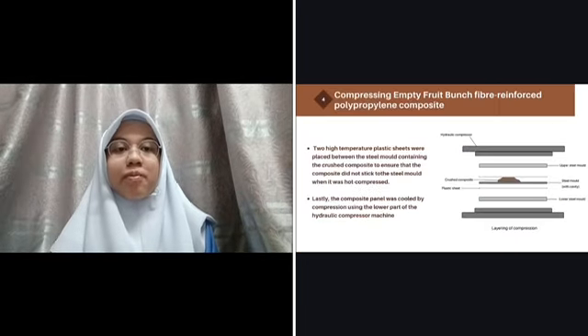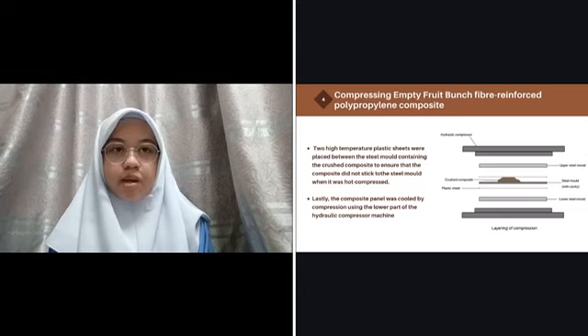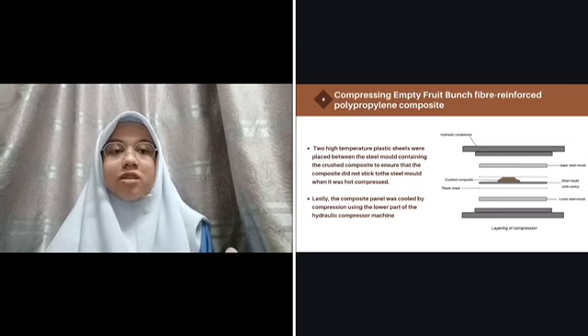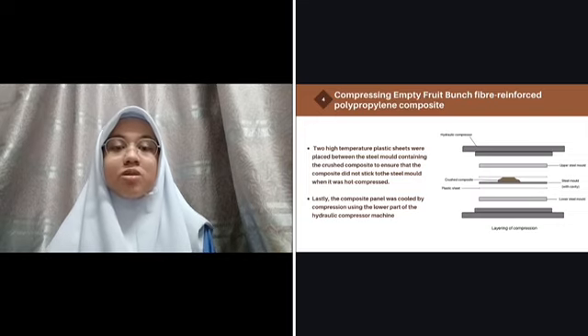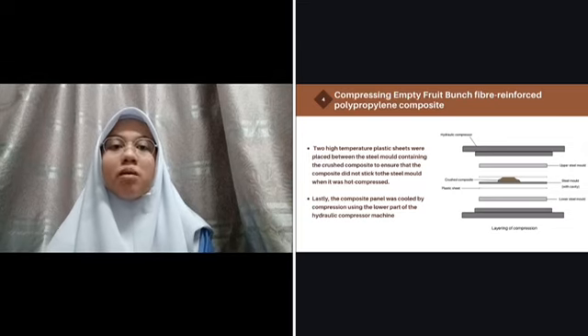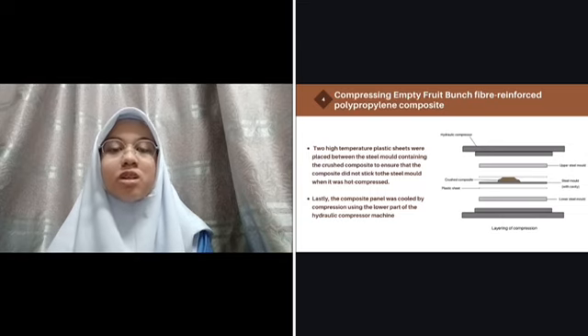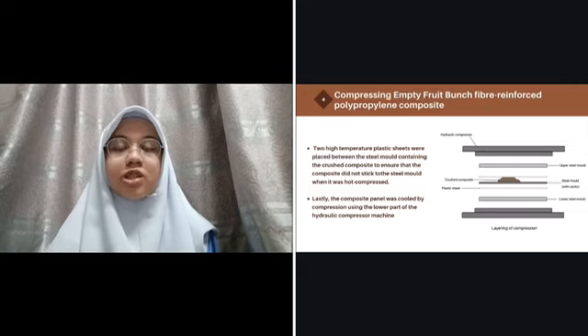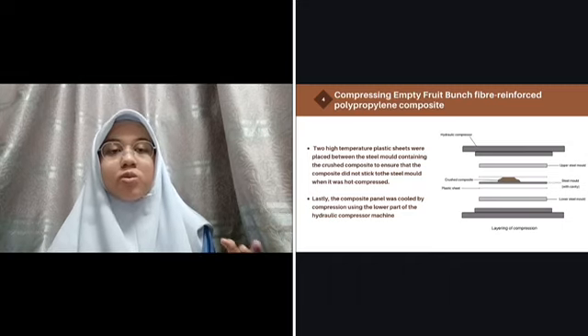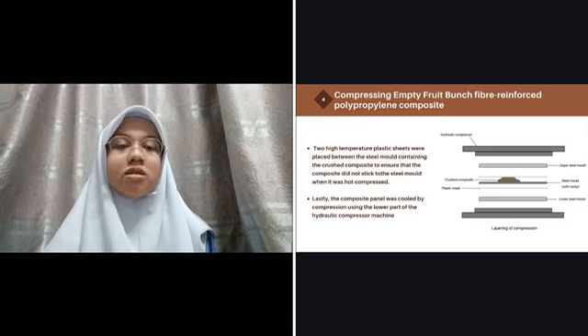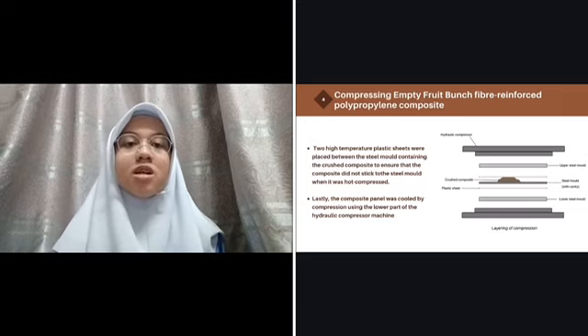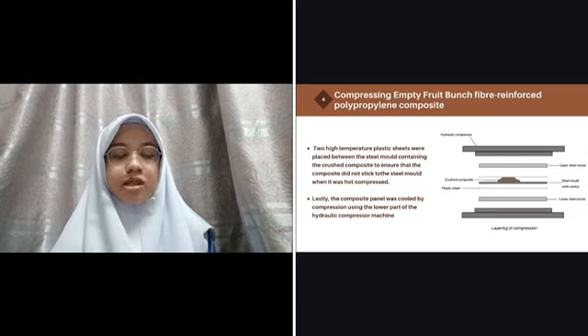And last step, we compress the empty fruit bunch fiber-reinforced polypropylene composite. Firstly, we put the crushed composite into a steel mold with a cavity of the sample size of the flexural strength test and also the tensile strength test that we will carry out after we obtain the finished product. Then the crushed composite in the steel mold will be preheated using the hot hydraulic compressor machine for about 15 minutes to ensure that the heat was spread throughout the crushed composite equally. Then we compressed the crushed composite again under the pressure of 150 kg force per square centimeter at 180 degrees Celsius for 20 minutes.